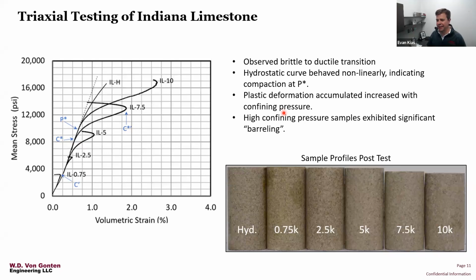That's an interesting question, Ed. I have to admit I haven't looked deeply into that. As the test progresses, the density of the sample is increasing, and with the increase in density we see an increase in velocity. However, you do see changes when the sample starts to dilate and the density goes down. Without looking at very specific cases, you can pretty much assume that the velocities will trend along with the density, and that density will trend along with the volumetric changes happening in the sample. I hope that touches your question.